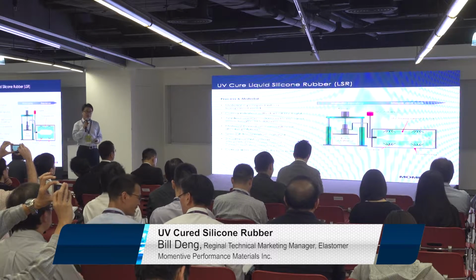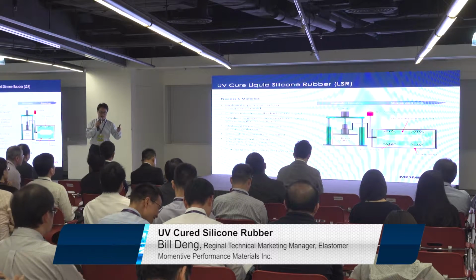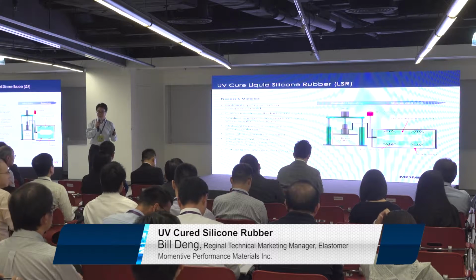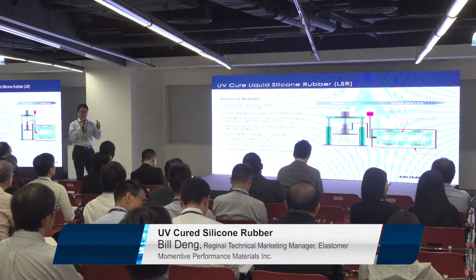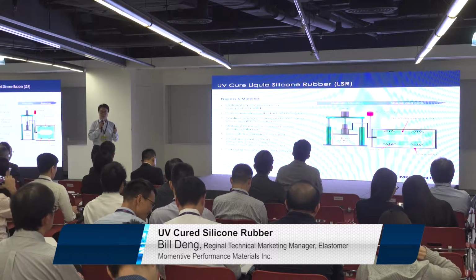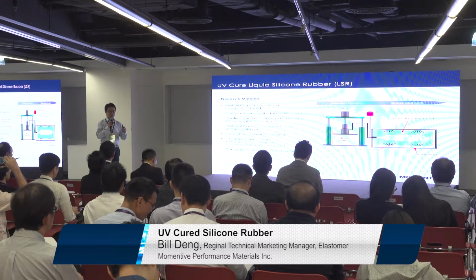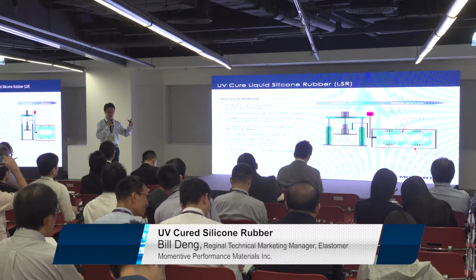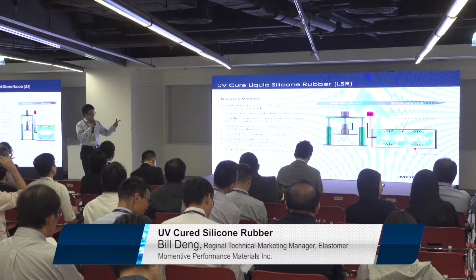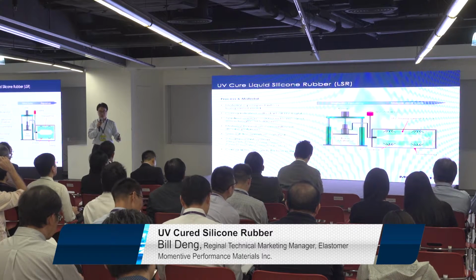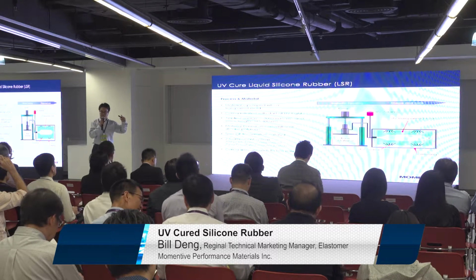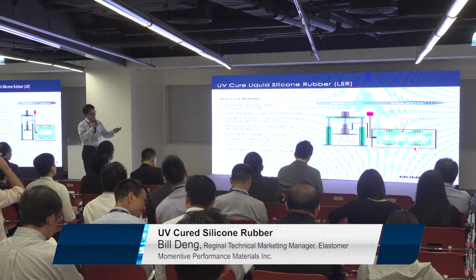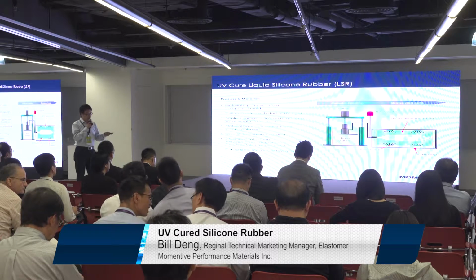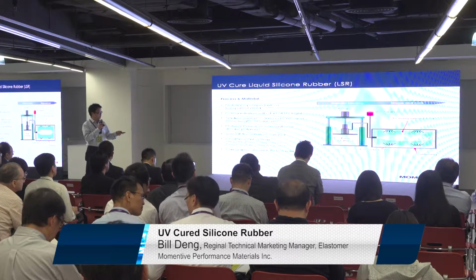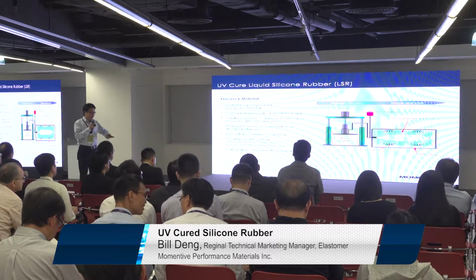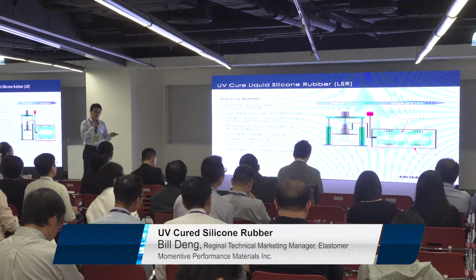But for UV LSR, you don't need to put the A part into the A part drum. We only have the B part as a base. And we have the A part, we call it catalyst, but the catalyst is only 2% with the B part. So you only need to put the A part into the dosing system in the injection molding machine. So if you are running the UV LSR system, you will see there is no A part, only B part in the machine. The A part is in the dosing system. Then that goes to the static mixer to get mixed. And the mold is also different, because if you need the material cured in the cavity, you need a transparent mold.